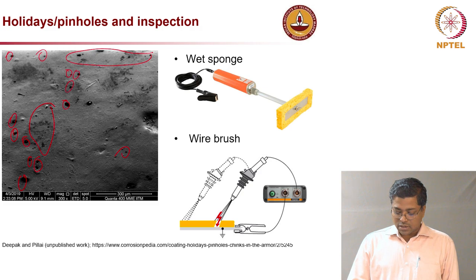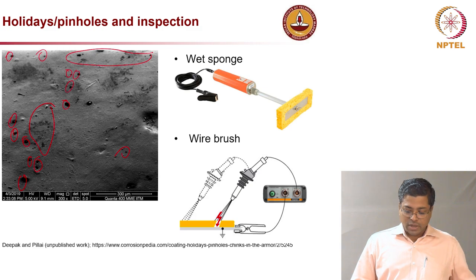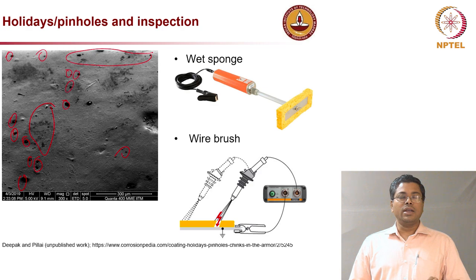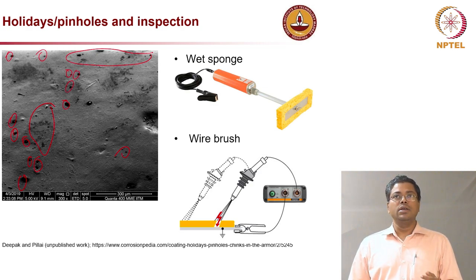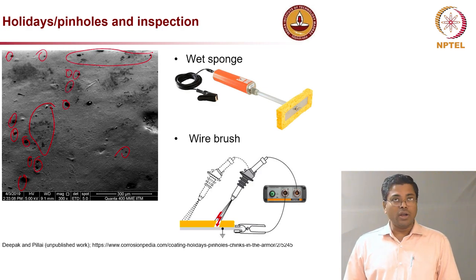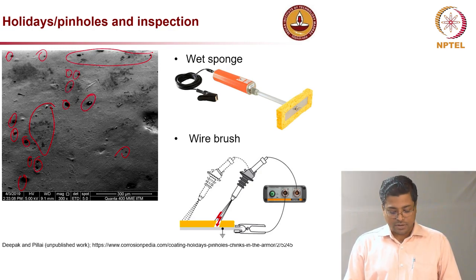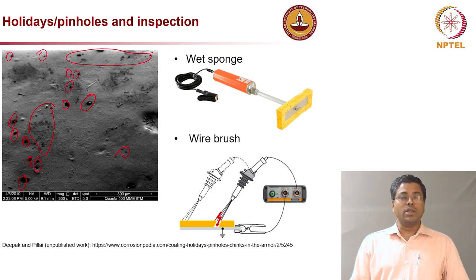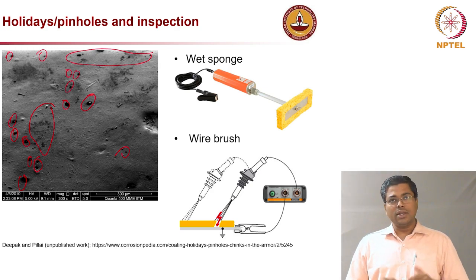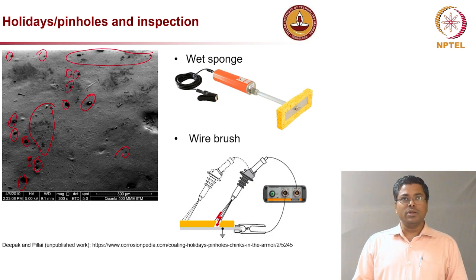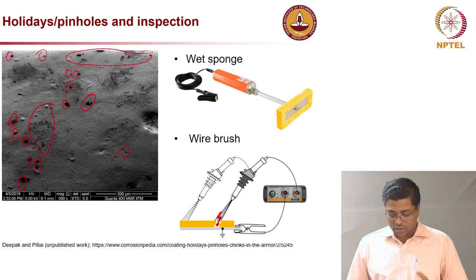There are two major types of equipment to check for pinholes: one using a wet sponge, another using a wire brush. You place the wet sponge or wire brush on the steel surface and make an electrical circuit. If there is a holiday, electrons will pass through and the circuit gets completed. If the coating is a very good insulator, the electrical circuit won't close — that's how we determine whether the coating quality is good or bad.